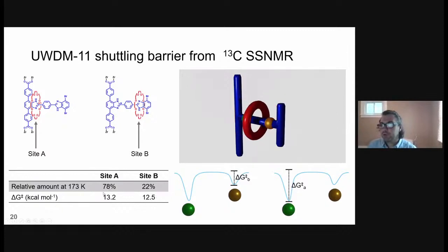With coalescence occurring at about 273 Kelvin, we can approximate an energy barrier for translation from going from site A to site B is 13.2 kilocalories per mole, and from site B to site A is about 12.5 kilocalories per mole. So this makes sense that the site that the end of the ring has a stronger affinity to has a larger energy barrier to break for it to move to the other recognition site.